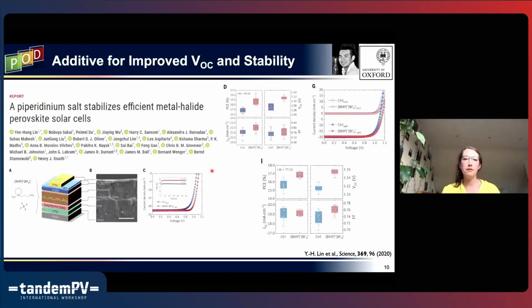So speaking of stability, we'll next move on to Yen's paper, which was the addition of this piperidinium salt into the FA-cesium perovskite in order to get really good long-term stability. So this piperidinium additive showed improved device performance across multiple device parameters, which is great. And it was also tested on a 90-10 iodide to bromide mixture and the 77-23 iodide to bromide mixture. And it improves the performance of both of those compositions. So that's really neat. This piperidinium salt, I should say, is mixed into the perovskite solution before spin coating. So it's not like a top treatment. It's actually mixed into the perovskite solution before it's deposited.